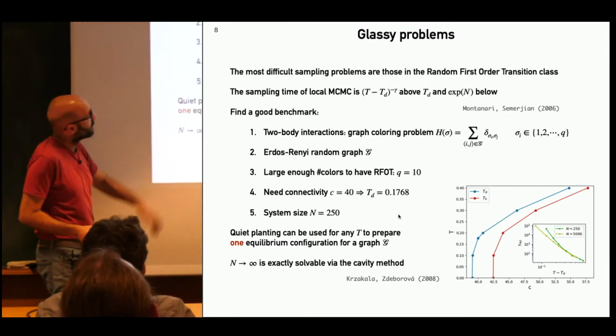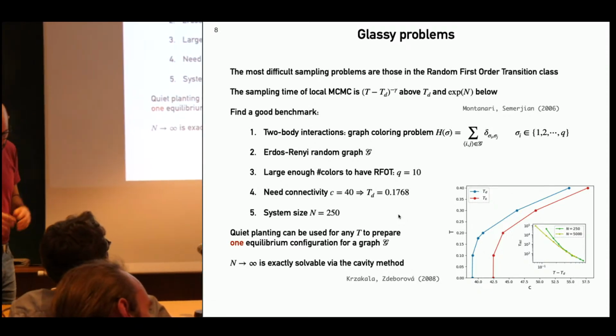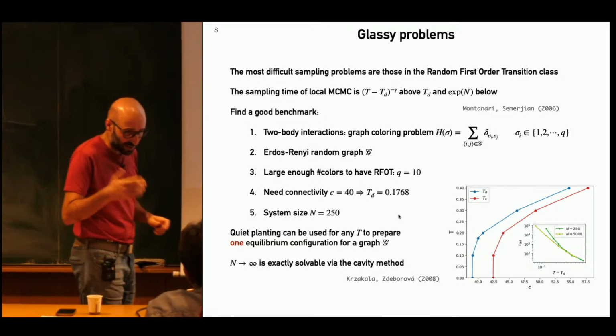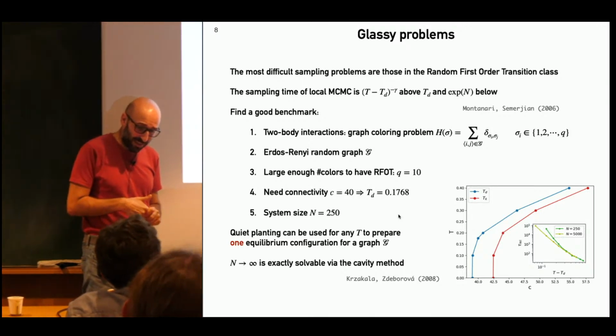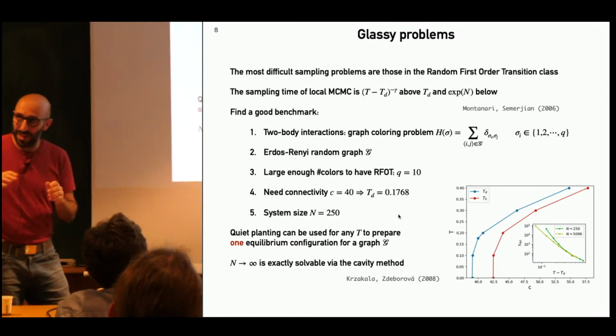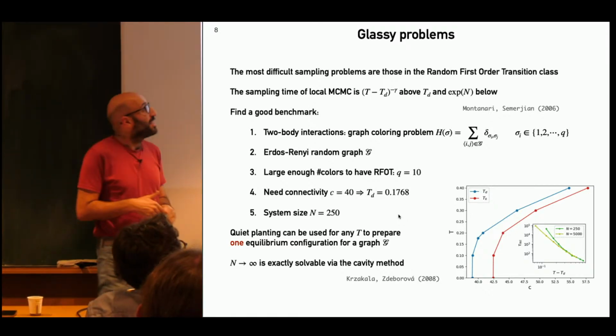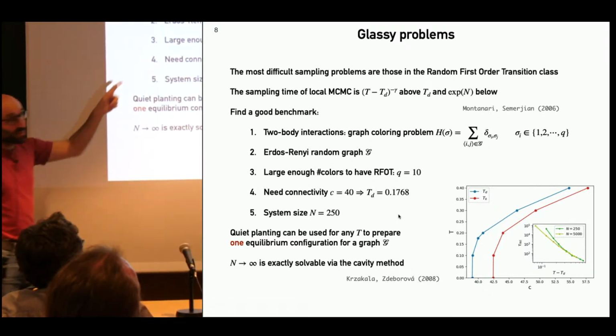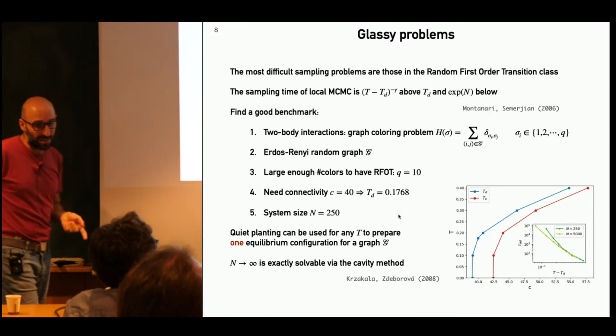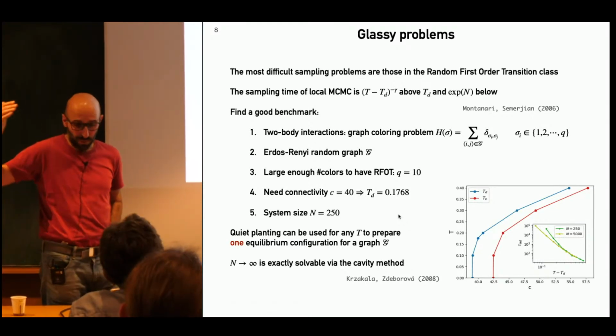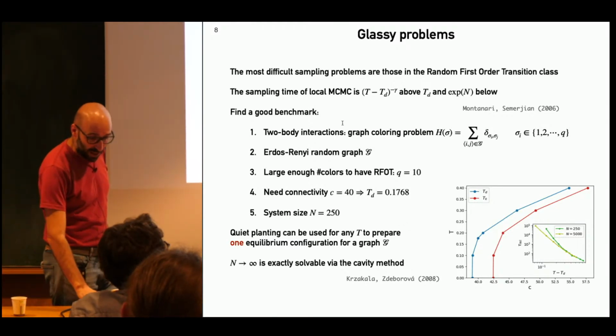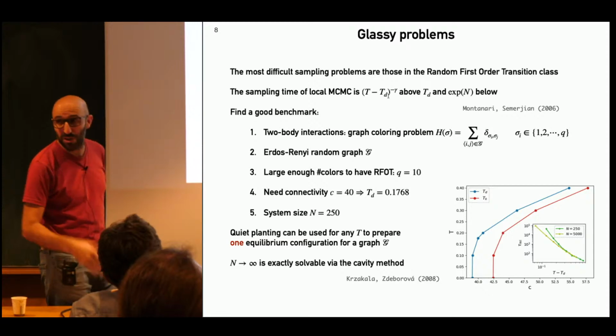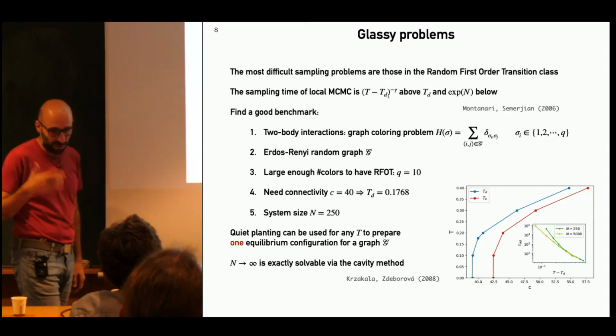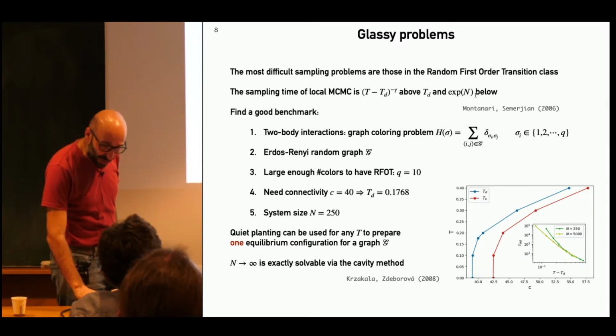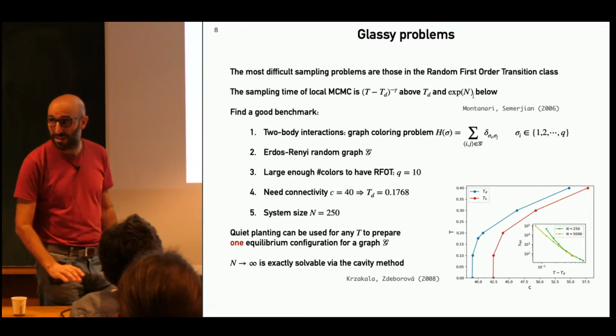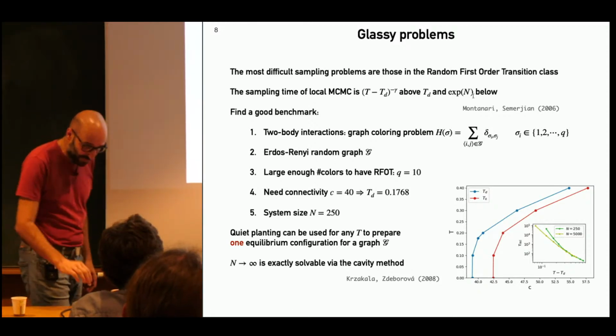And glasses belong to this, at least in mean field, this random first-order transition class that Olivier introduced yesterday. What you can prove, again rigorously in mean field, is that the sampling time of local MCMC is finite at high temperature, but it diverges as a power law when you reach a certain transition, the mode coupling transition or dynamical transition. And below that, it's exponential in the size of the system.